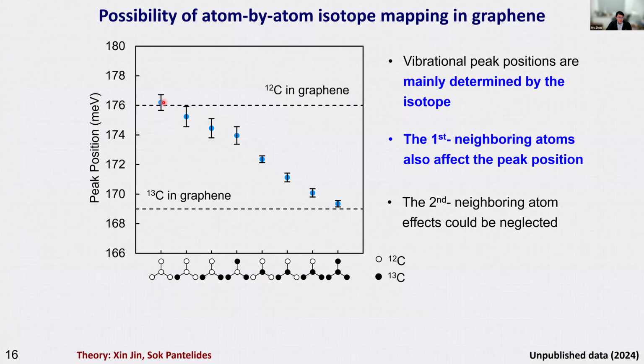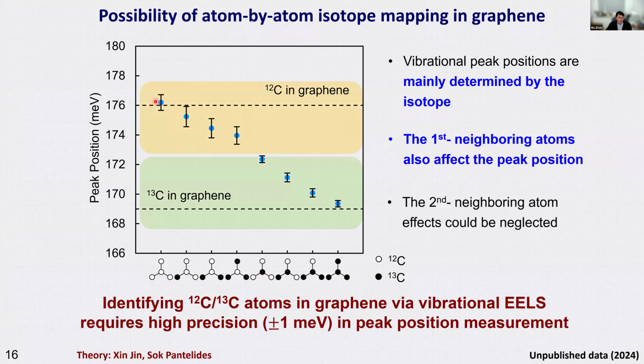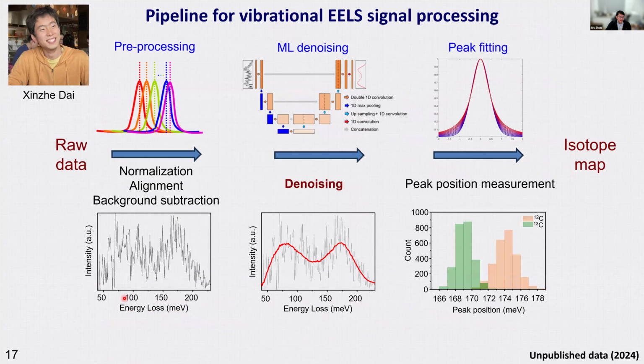So what we see is, if you're looking at the optical phonon mode, and just looking at the peak position, we see that a carbon-12 center atom always has a higher vibrational frequency. When you are looking at a carbon-13 atom, no matter how it bonds with the neighboring atoms, you always have a lower frequency. But the difference between these two is small. So that means that if we want to do atom-by-atom isotope analysis, we need to have plus or minus 1 milli-electron volt accuracy in identifying the peak position.